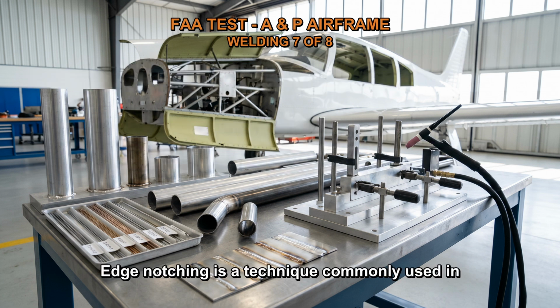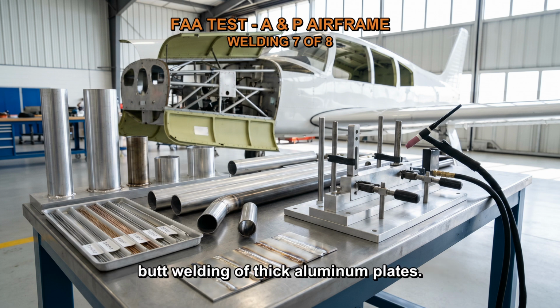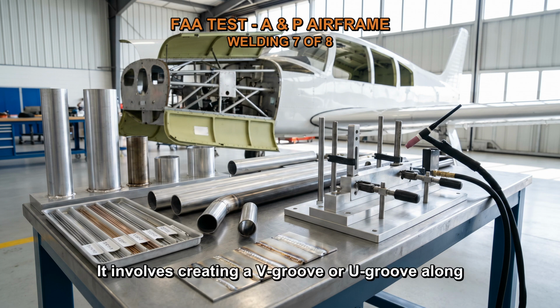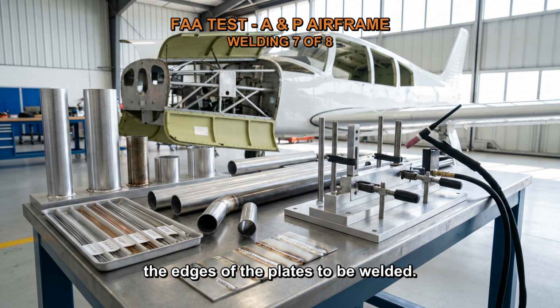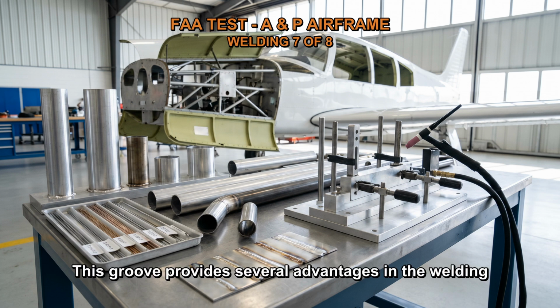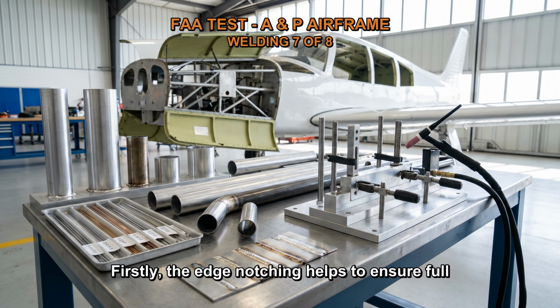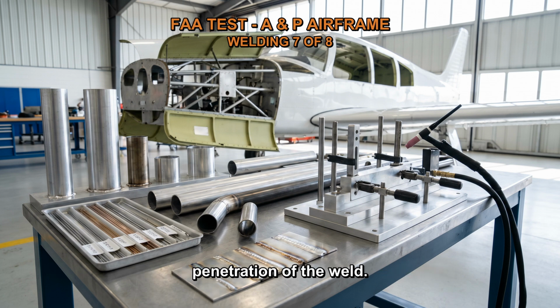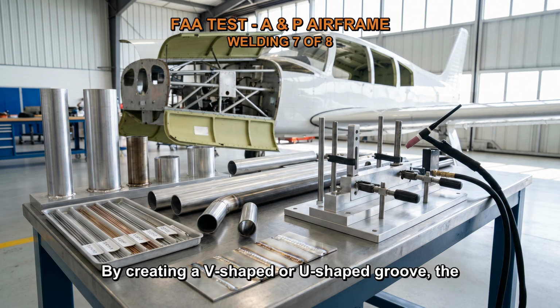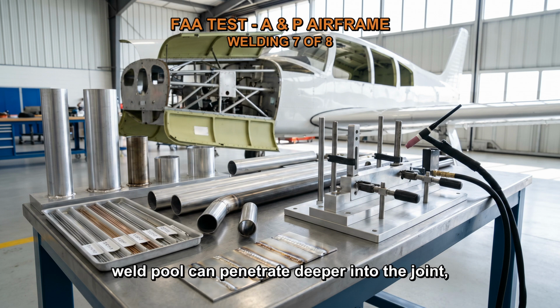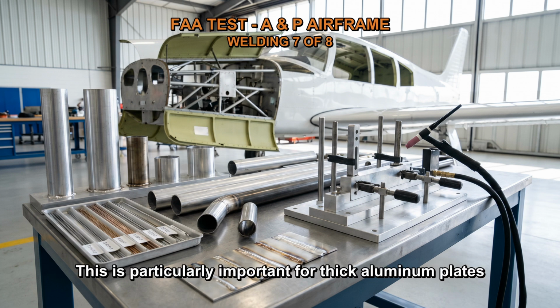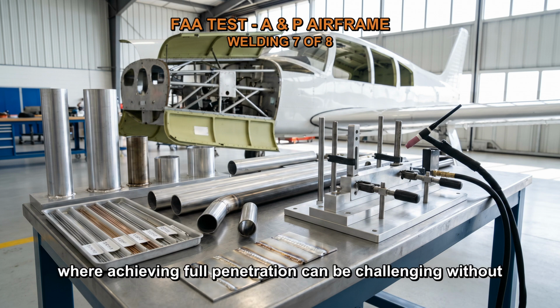Edge notching is a technique commonly used in butt welding of thick aluminum plates. It involves creating a V-groove or U-groove along the edges of the plates to be welded. This groove provides several advantages in the welding process. Firstly, the edge notching helps to ensure full penetration of the weld. By creating a V-shaped or U-shaped groove, the weld pool can penetrate deeper into the joint, resulting in a stronger and more reliable weld. This is particularly important for thick aluminum plates where achieving full penetration can be challenging without edge preparation.